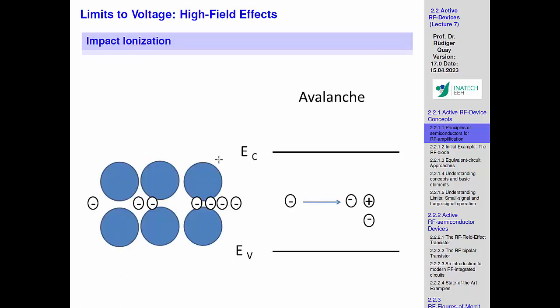Why is that happening, and what is the main cause? Why are hot carriers so critical? What is happening there? I told you this image of the electron traveling and then being bumped by the phonons, bang, bang, bang. But this is not the only thing, because when we get these pronounced high fields, despite the phonon braking, they're immediately accelerated again, because of the high field gradients. And what you get then, the electrons start to multiply in the crystal. Yeah, and there are different mechanisms. The most well known is the